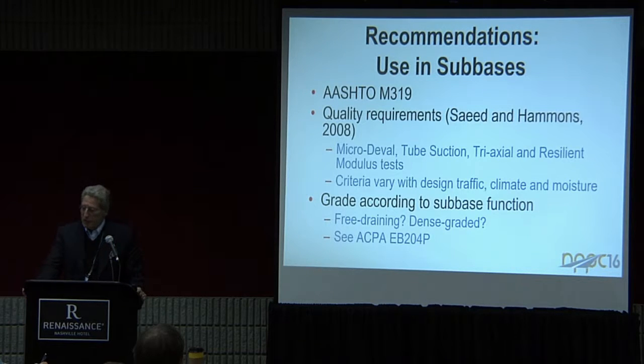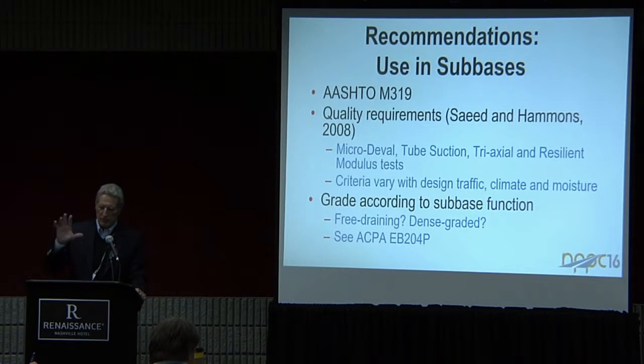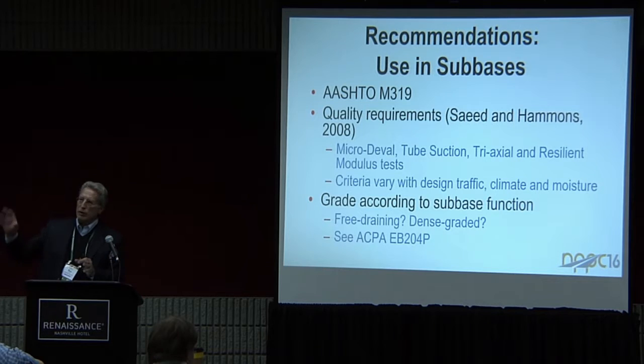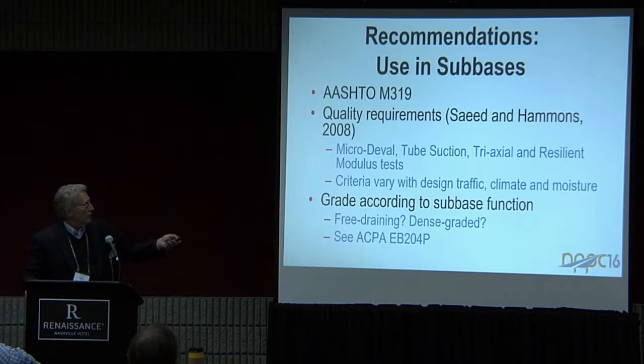There is an AASHTO specification. M319 covers the AASHTO recommendations for using crushed concrete in subbase materials. There have been some NCHRP studies done recently as well. One that was completed about 8 years ago by Attar Saeed and Mike Hammons developed a series of quality requirements for different uses of crushed concrete in bases. They adopted tests like the micro-Deval test into a matrix that said that if you have a certain level of traffic and a certain environment that you're constructing in, freeze-thaw climates and moisture condition, then these would be the requirements for each of these tests that are listed here.